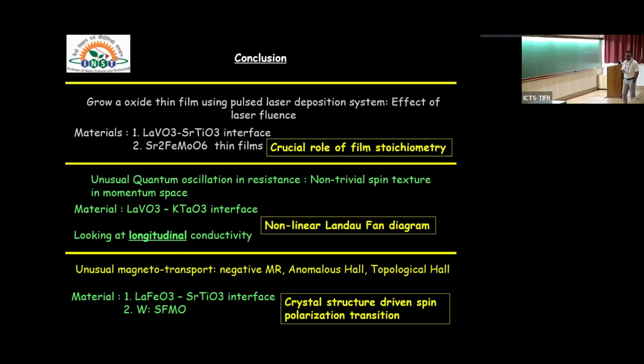First, we show the strength of a pulsed laser deposition system, where you can change the laser fluence and you can vary the stoichiometry of the material and see very interesting properties. Second, we have shown that if you have some non-trivial spin texture possible in momentum space, then that should be reflected in the longitudinal conductivity as a non-linear Landau fan diagram. And third is the unusual magnetotransport: negative magnetoresistance, anomalous Hall effect, and topological Hall effect. And we are working on this.